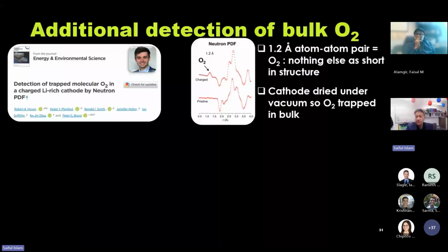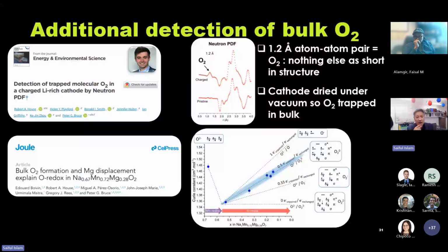We've also done some SQUID measurements, some magnetic measurements on a different material, a sodium manganese magnesium O2. And if you look at the magnetic data as a function of charge, shown on the bottom right, the actual magnetic data shown in blue, the blue dots, which is the Curie constant, it only ties up with molecular O2, triplet O2. The other oxygen species, dimer species, or oxygen O- species do not tie up with that magnetic data.